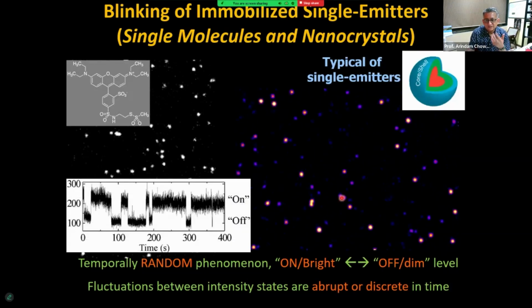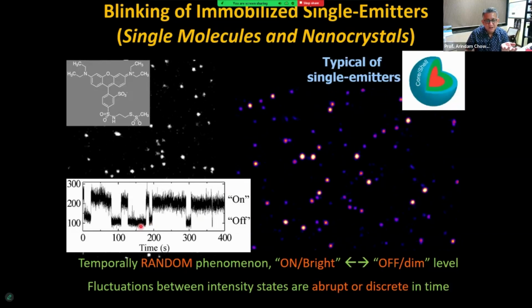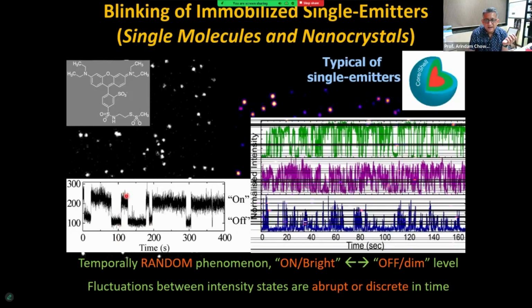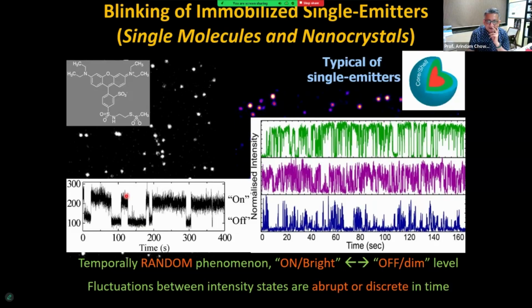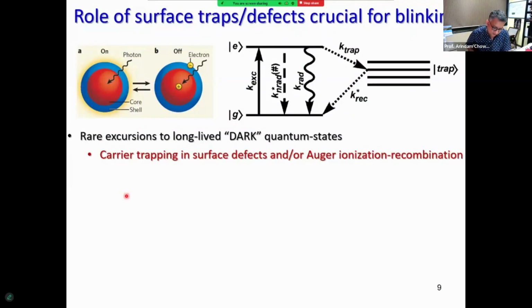And this process, if I plot it, it will look like this. You can see these abrupt jumps that are going on over here. And same is true for nanocrystals. And this process essentially has been explained. I'm giving you the case of nanocrystals: when you shine light on a system, you can generate an electron and a hole, which is often called an exciton. And once the system has generated the exciton, this quasi-particle can recombine and it can emit light. And this kind of cycling process of absorption and emission continuously goes on. And as long as it goes on, there's no problem, light comes out.